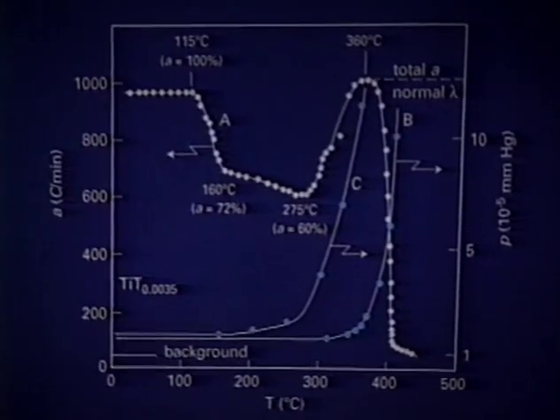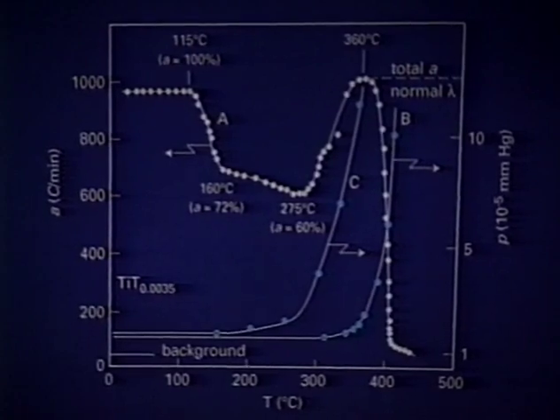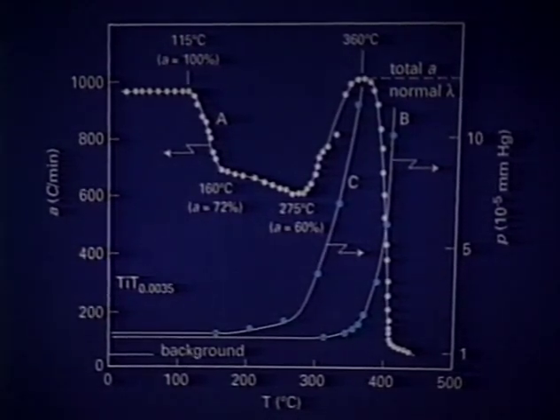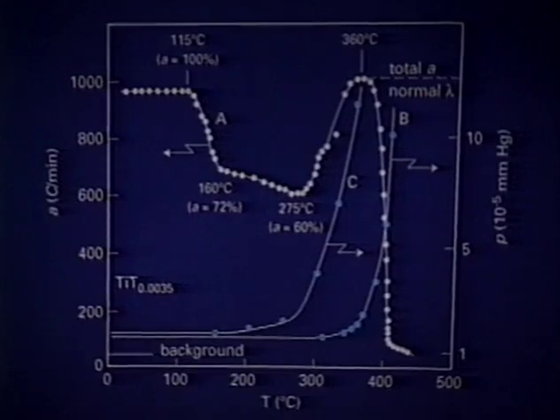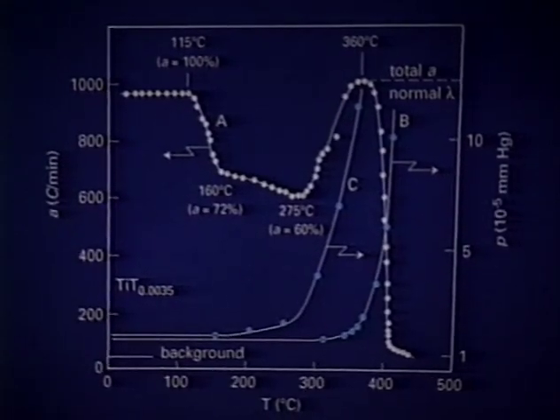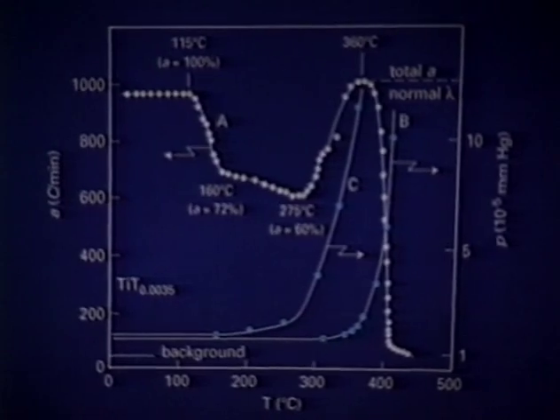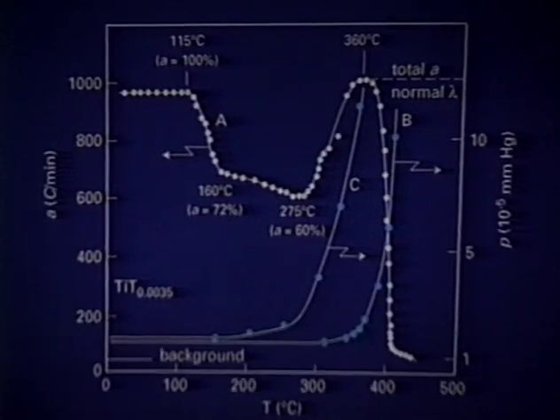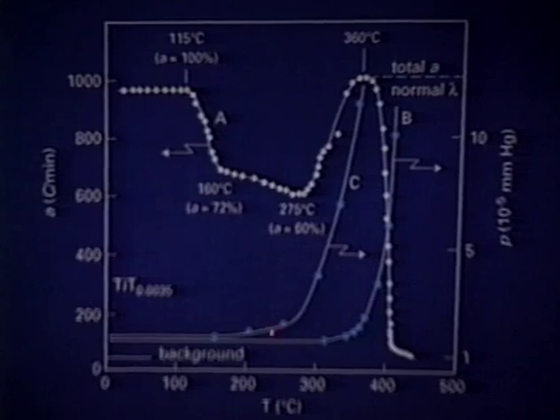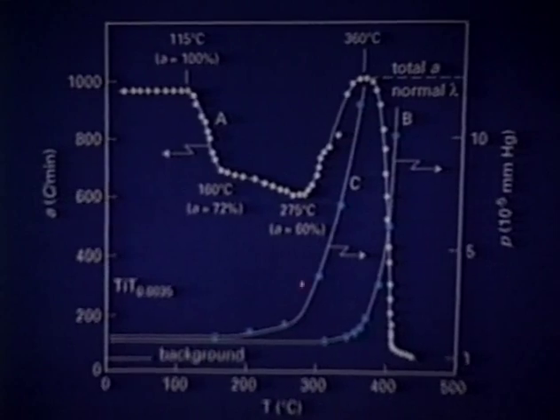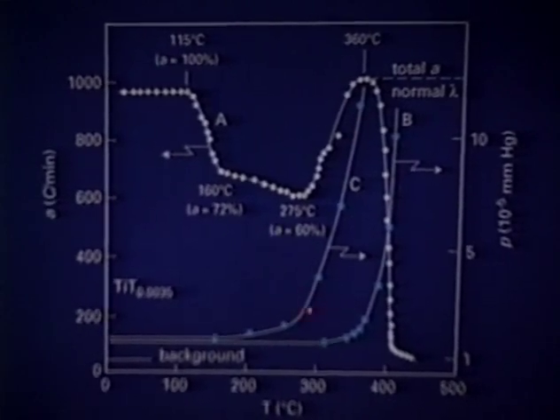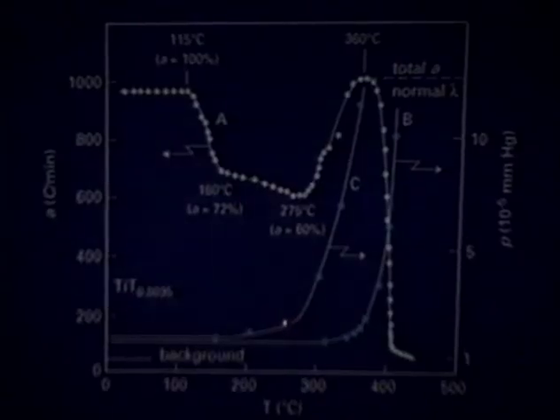This conclusion, which is very important, has to be ascertained by further experiments applying ultra-high vacuum technique to definitely determine oxide layers on the surface of the titanium particles. But from this conclusion, we can say that the second increase of pressure shows us the release of the tritium atoms from the titanium lattice.